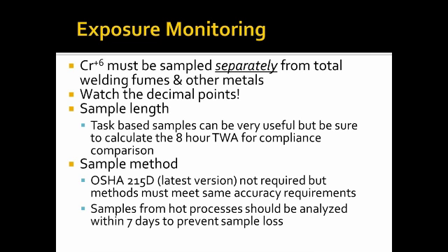Sample methods, OSHA 215D. The latest version is not necessarily required, but my finding is that that's what labs are using. Another thing to keep in mind is that there is sample loss from samples generated from hot processes, so be sure to have those samples analyzed within 7 days. The sooner the better to prevent sample loss.